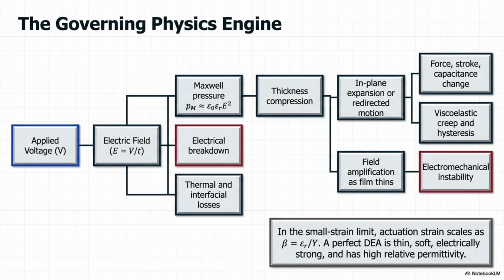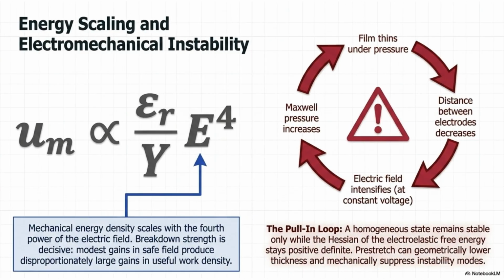This flowchart details the governing physics engine for DEAs. Applied voltage creates an electric field, which can lead to Maxwell pressure or electrical breakdown. Maxwell pressure causes thickness compression, which in turn leads to expansion and motion. Mechanical energy density scales with the fourth power of the electric field. Breakdown strength is critical, as modest gains in the safe field produce disproportionately large gains in useful work density. The pull-in loop illustrates the instability risk.